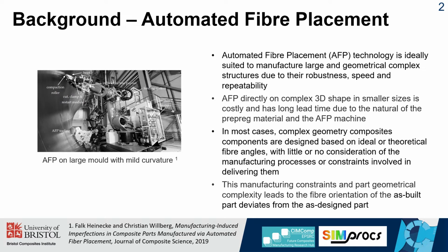As a result, many machine parameters need to be adjusted, and all these parameters can affect the final quality of the layup. Therefore, this technique is not perfectly suited to manufacture small to medium parts with complex geometry, as deviation between as-designed and as-manufactured parts is almost inevitable, as well as the occurrence of process-induced defects.